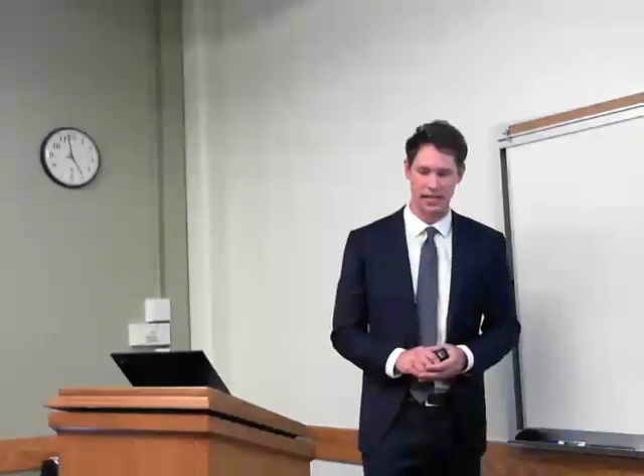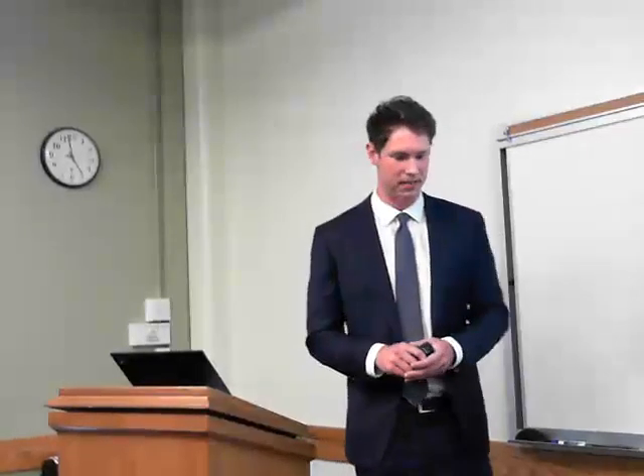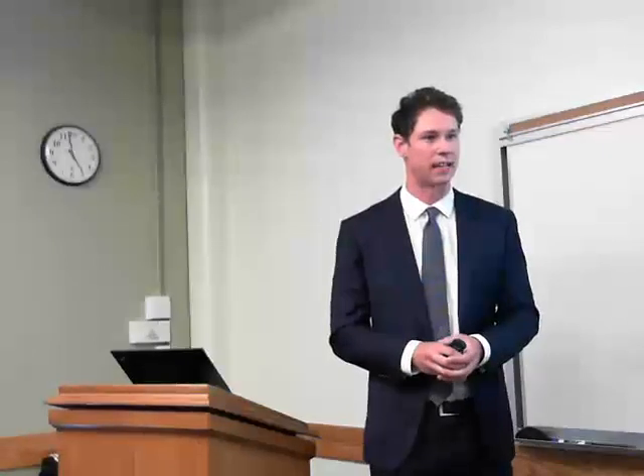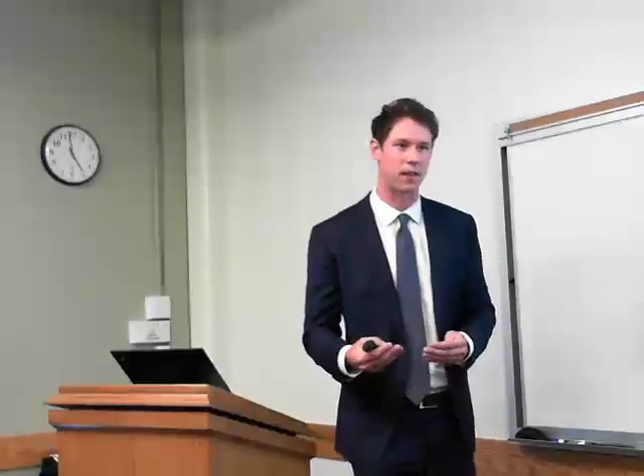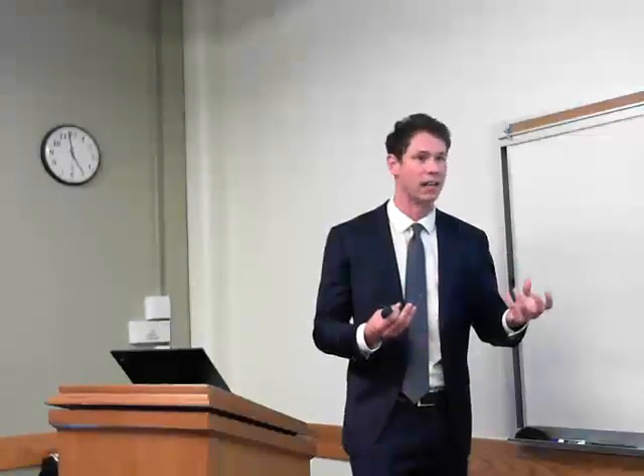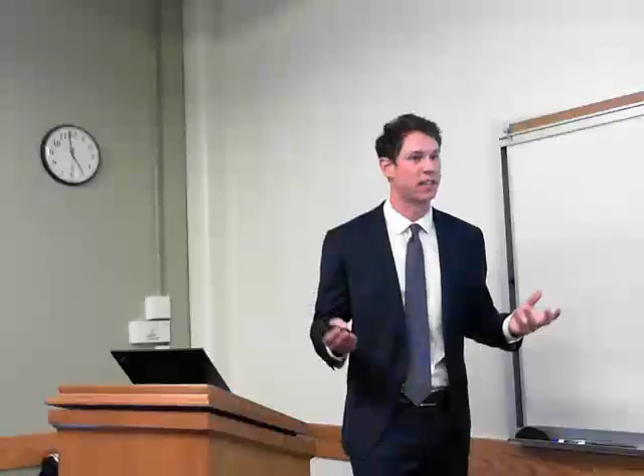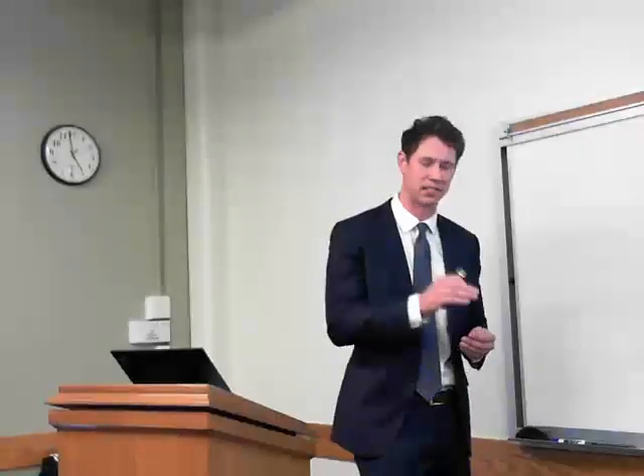Another thing that changes that's interesting is the color, and that's something I've been looking at lately because this is somehow related to the oxidation state of our cations, most likely. That's something that I don't think anyone has really characterized, but often we'll put in a material like thorium dioxide where it's a frank white, and when we take it out, it's dark green or something like this. So I don't know exactly what that means, but that's more evidence of really dramatic changes going on in the crystal chemistry of these materials.